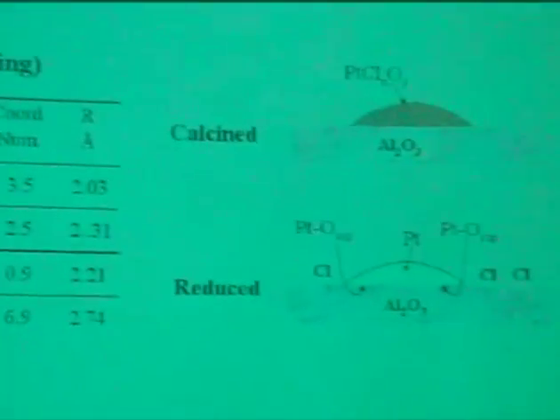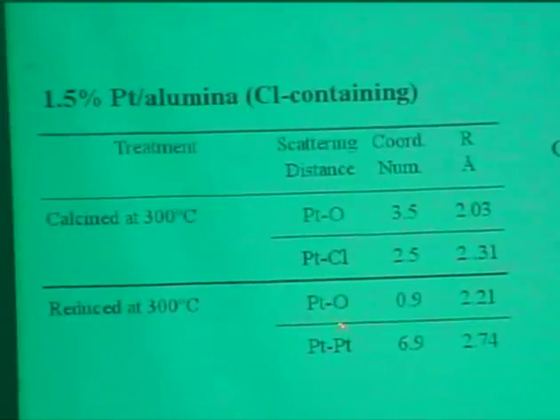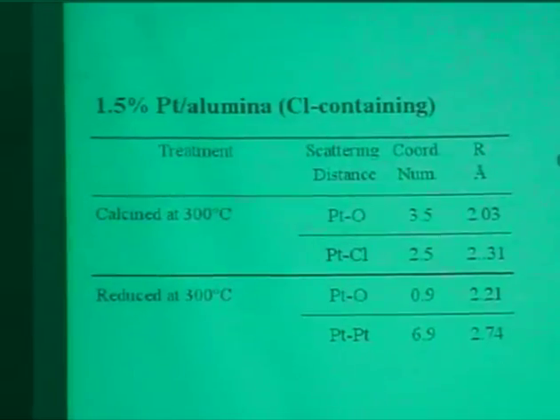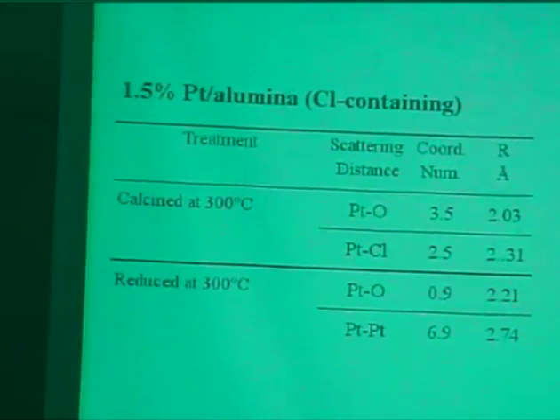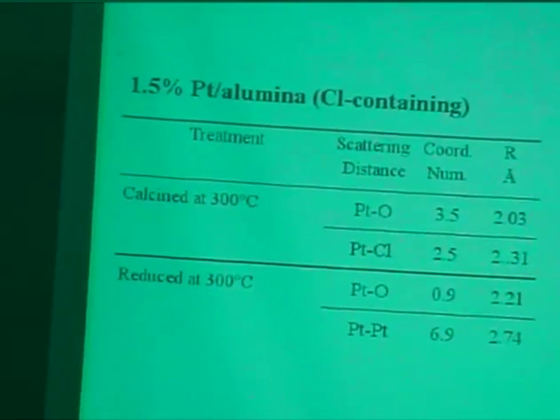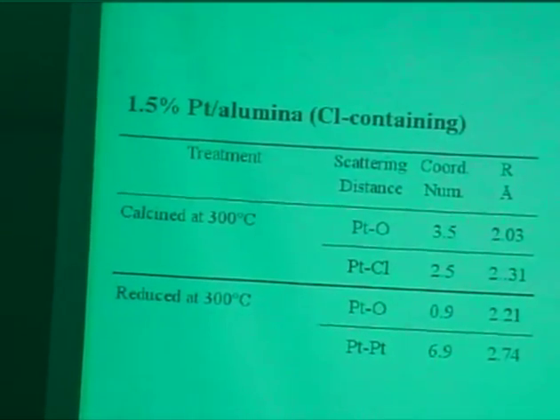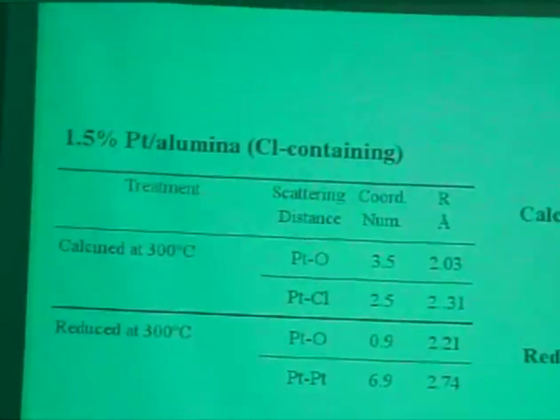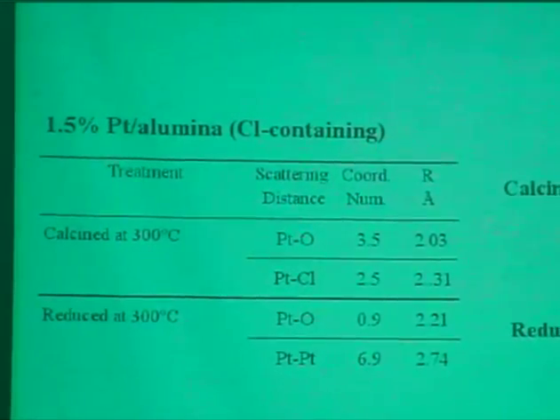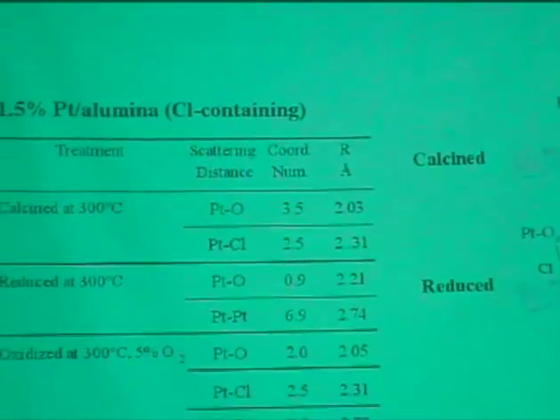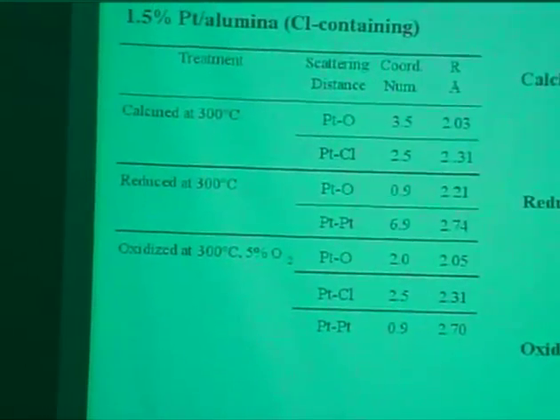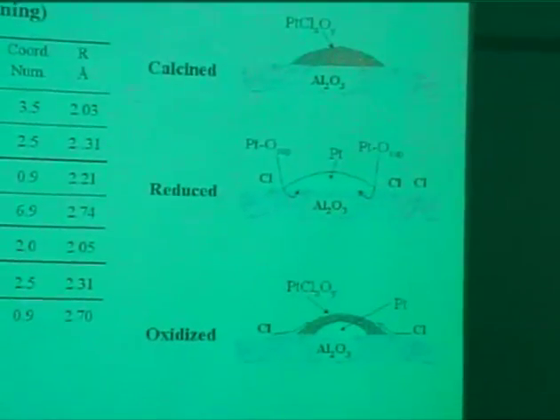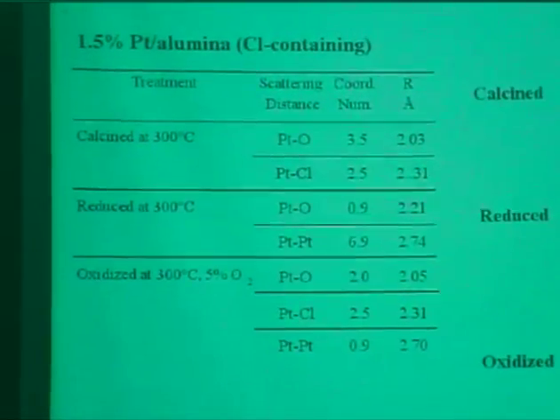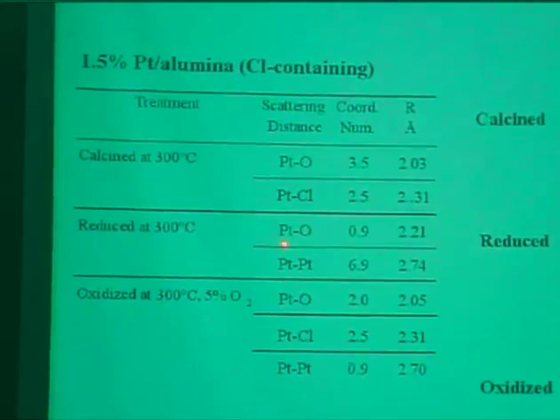And again, when we reduce, similar results: the right coordination numbers and distances, some of the platinum oxygen due to the support here. And now you see that we put the chlorine out of there, because the reduction sends the chlorine out. And the interesting thing, which really confirmed everything we've done with the activity, was that when we oxidize this, we see again the appearance of platinum chloride. So what happened is that the chlorine that was here went back to the surface.